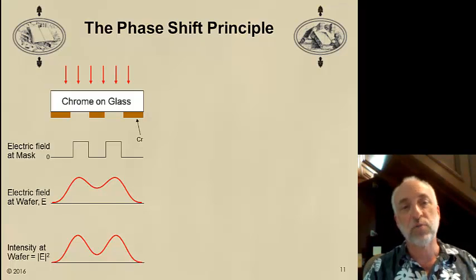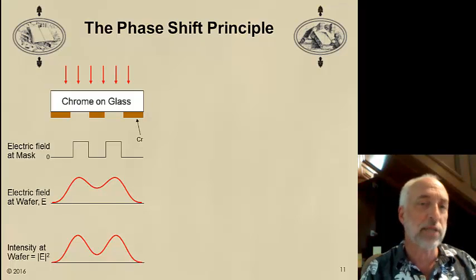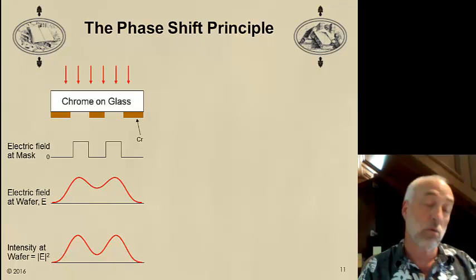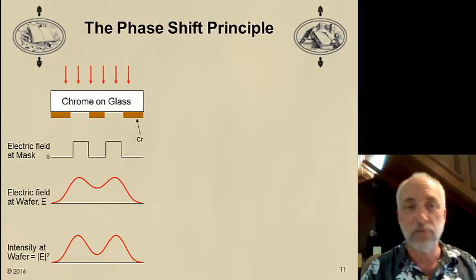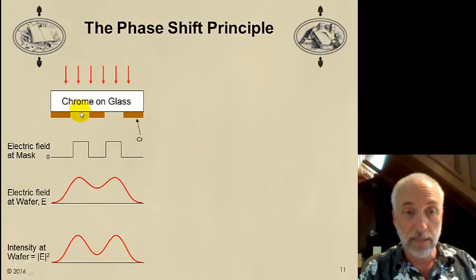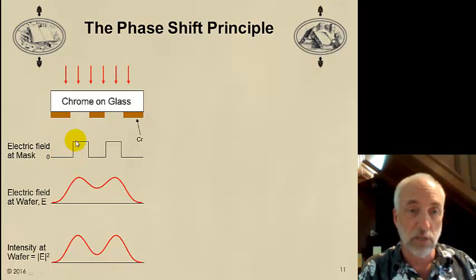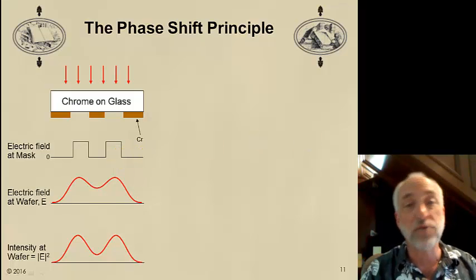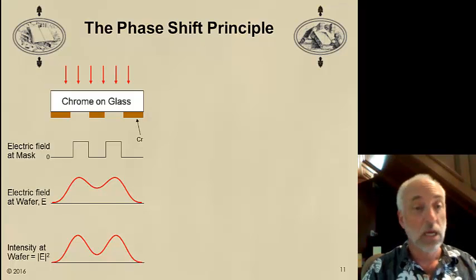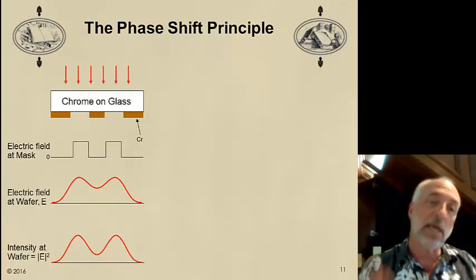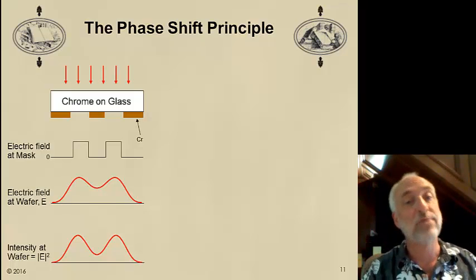Well, I'll show you the phase shift principle by first comparing to a chrome-on-glass mask. So the chrome-on-glass, or any absorber on glass, is a binary transmitting material. Light going through the glass, we say, has a transmission of 1, so the electric field right at the bottom of the mask will say has a value of 1, and no light makes it through the chrome, so its electric field just going through the mask is 0. So kind of an idealized transmission function is the electric field at the mask. It's 1 or 0, depending on whether we're underneath the chrome or underneath the glass. However, as the light propagates away from the mask and goes through the lens and is imaged onto the wafer, we have diffraction.